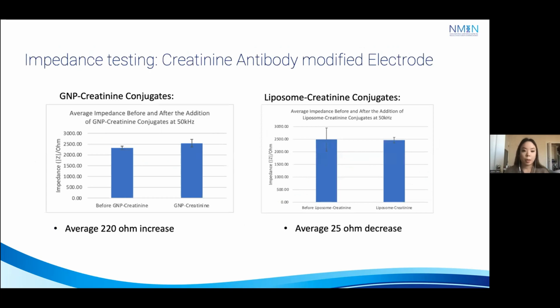And we were able to observe similar trends in our creatinine test as well, where we saw after the addition of gold nanoparticle creatinine conjugates, an average of a 220 ohm increase in impedance. And then after the addition of the liposome creatinine conjugates, we were able to observe an average of a 25 ohm decrease in impedance.